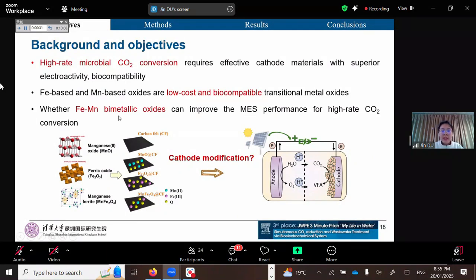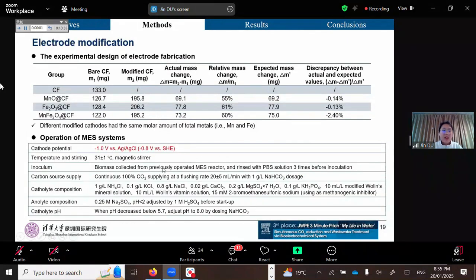Moreover, the bimetallic oxides often exhibit superior properties compared to the monometal oxide because of the synergistic effects of 2 metals. That's why we chose iron and manganese bimetallic oxides for cathode modification in this study. So we modified the carbon felt cathode with manganese oxide, iron oxide, and manganese ferrite bimetallic oxide. The manganese ferrite powder was synthesized through the co-precipitation and hydrothermal methods and loaded onto the electrodes by drop casting. Then 4 microbial electrosynthesis reactors using prepared electrodes were operated.